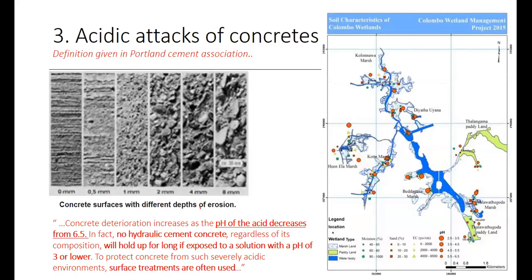So, the acidic attacks. Now we have already covered carbonation and chlorination. The remaining part is small: acidic attacks. Based on the Portland Cement Association's definitions, if the pH value of an acid or of a soil goes less than 6.5, they categorize it as an acidic exposure condition. Usually, no hydraulic cement concrete, hydraulic cement meaning conventional cement or fly ash or slag, which deliver hydraulic reactions, can withstand a pH value of less than 3 or lower. Those I have taken from the same research paper.